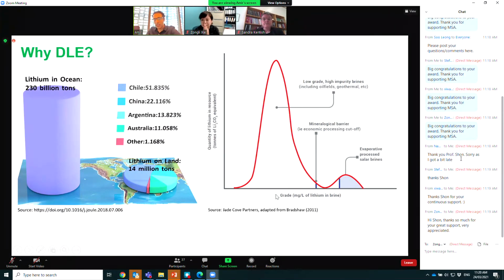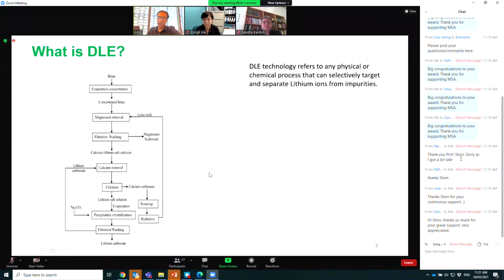This graph shows the lithium grade, the lithium quality grade. This is the mineralogical barrier below which it's not economical to extract lithium. The majority of the companies are focusing on the high quality grade, whereas the main sources of lithium are in this area. But as I said, there isn't currently a technology which can extract lithium in an economical and sustainable way. Because of the increasing demand for lithium and the concern related to the environment, that creates a driving force for industry and academia to create technologies that shift us toward the left of this graph, and extract lithium from those types of resources. So what is DLE?